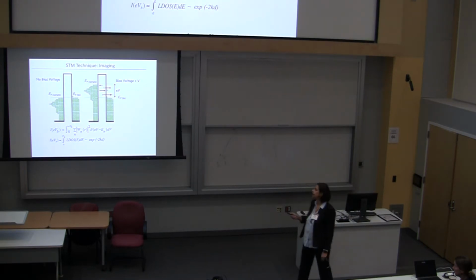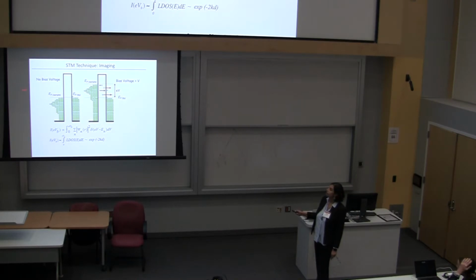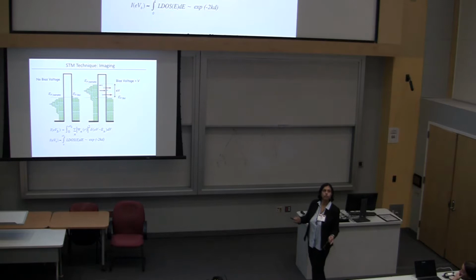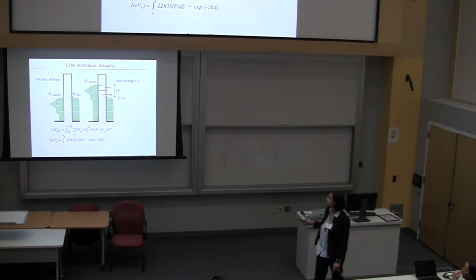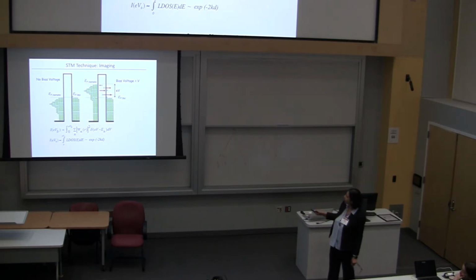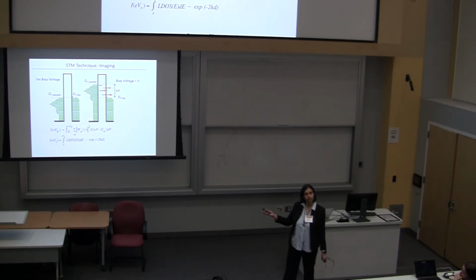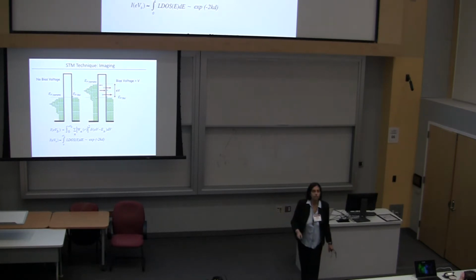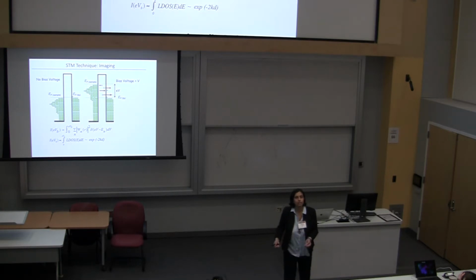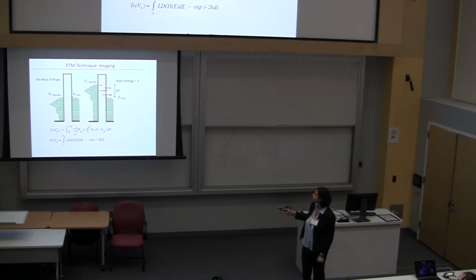So how does the STM work? When you bring the tip and the sample in close proximity, the Fermi levels instantaneously line up, because electrons flow from one to the other by tunneling. Now when you apply a bias voltage, let's say you raise the Fermi energy of the sample with respect to the tip. You can see what will happen: the electrons from the filled states of the sample will tunnel into the empty states of the tip. So your tunnel current is proportional to the integrated density of states of the sample from EF to this point, as well as the density of states of the tip. We want to make sure that the tip doesn't affect our measurements too much, so we try to find tips where the density of states is pretty constant. We try to take the tip out of the picture by doing that.